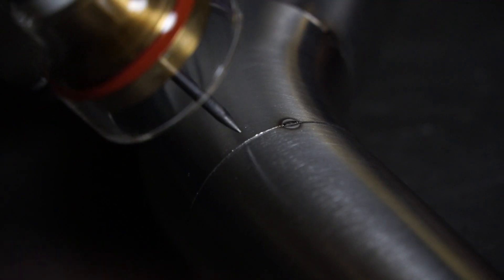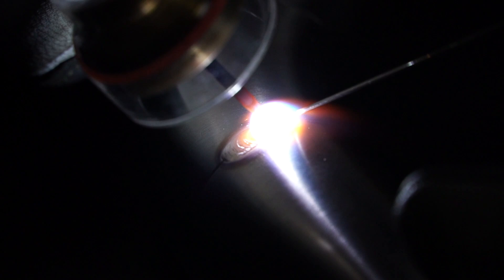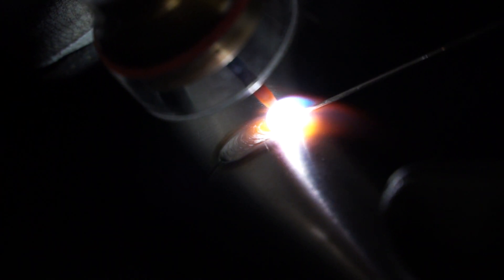When welding anything, it's like driving a five-speed transmission. It's a balancing act with your throttle and your clutch. If you are moving too fast with not enough heat, your weld will look clumpy and cold. If you are moving too slow with adequate or too much heat, you're going to overheat your part and your weld will appear dull and overheated.